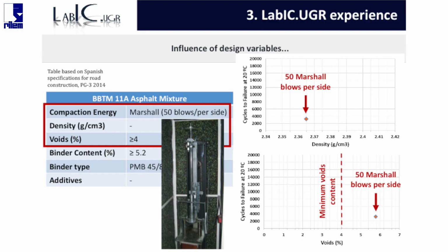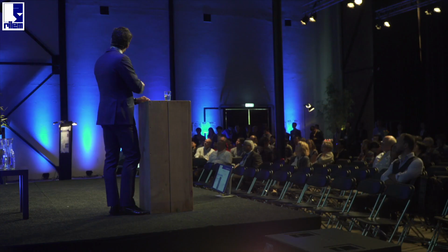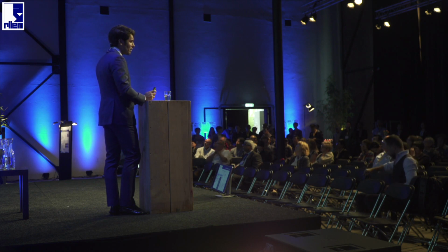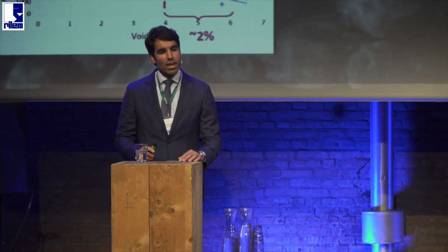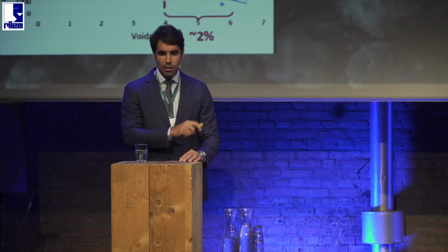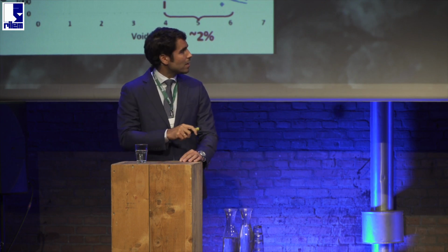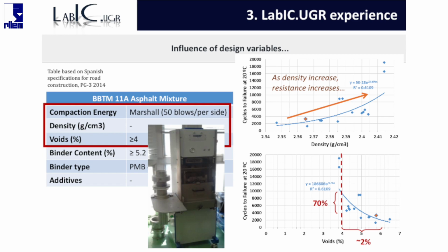are going to obtain a material that has around 6%, for example, that accomplishes the criteria, and with a density and a resistance in the fatigue asphalt cracking test of around 3,000 cycles. That's okay. But if we change the compaction energy used in the material, it is observed that as the density increases, the mechanical resistance of the material increases. That means that not all asphalt material, not all additives, will have the same compaction energy.